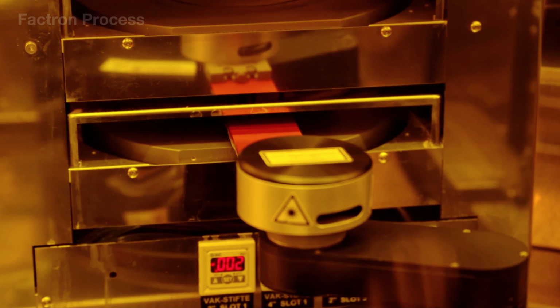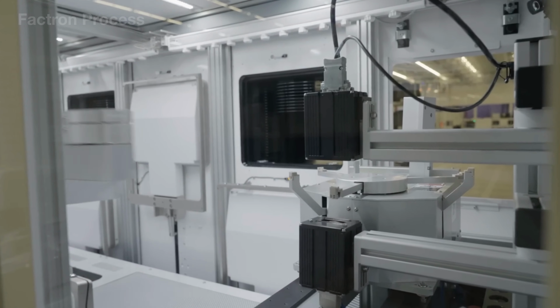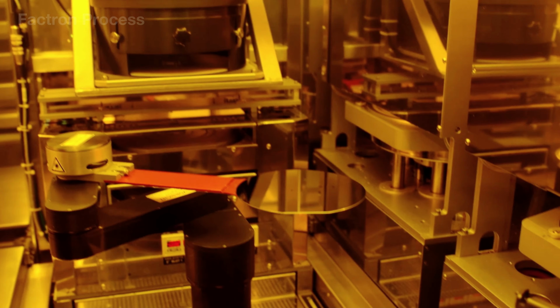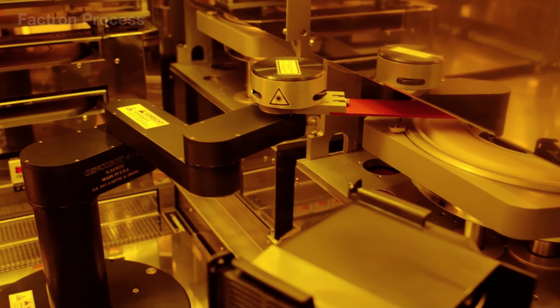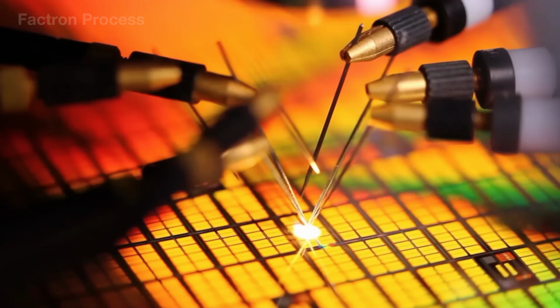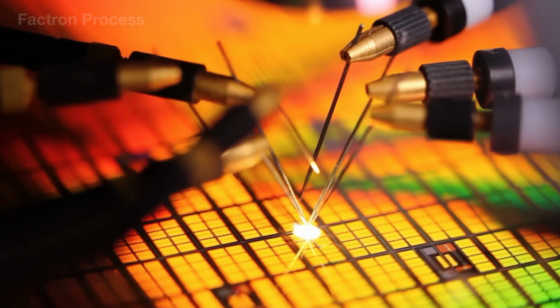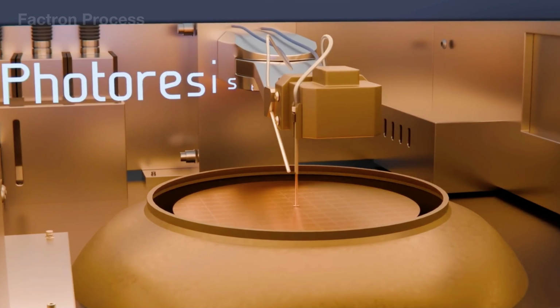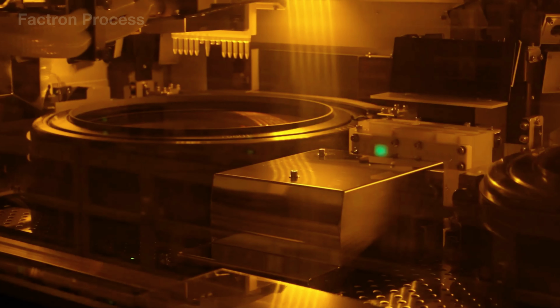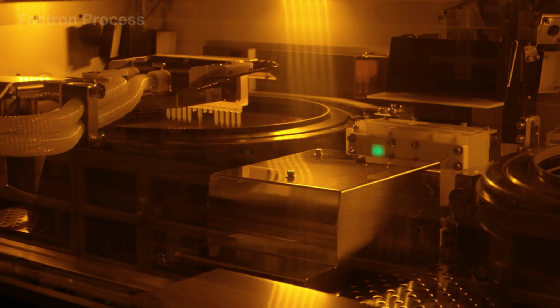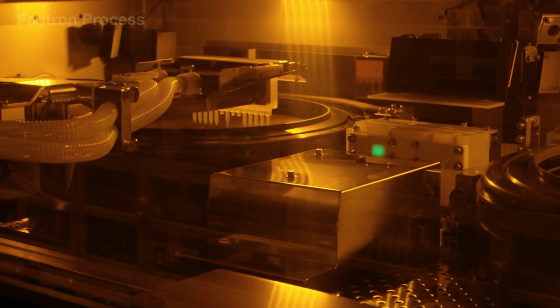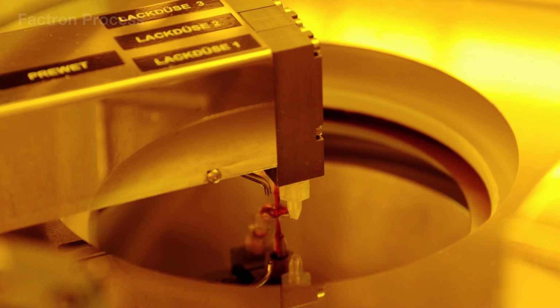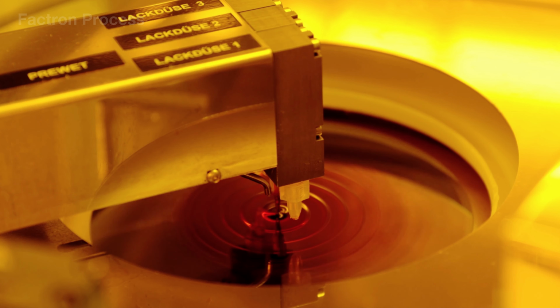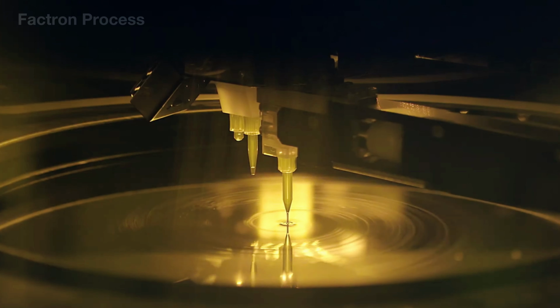Once the semiconductor layers have been grown, the wafer is still nothing more than a flat surface. To transform it into thousands of individual LED chips, the factory uses photolithography, a technique similar to printing an extremely tiny pattern onto the wafer with light. First, a light-sensitive material called photoresist is deposited onto the wafer, which is then spun at several thousand revolutions per minute. Centrifugal force spreads the liquid into a thin, uniform coating before the wafer is baked at approximately 194 to 230 degrees Fahrenheit.